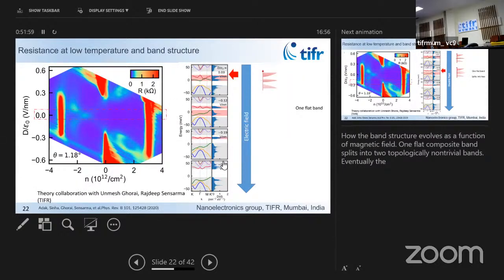So this was some earlier work. The first work that we did was a collaboration with Rajdeep and student Umesh, which allowed us to understand. So when we measure the electrical transport, this cartoon is what we can focus on. So this band structure is something like this. I have one flat band or 2 superimposed flat bands, and then 2 bands, remote bands, which are widely moving in energy, something like that. So this goes on, but then you have a set of states which are narrow in energy.